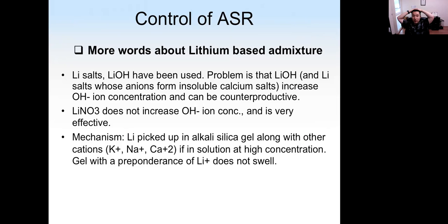So more words about lithium-based admixtures. Okay, so the problem for that is lithium hydroxide may increase concentration of hydroxide ions. So, more hydroxide ions, which may generate more potential ASR. We increase alkali concentration because of that. So if we do not use lithium hydroxide, we use lithium nitrate, so that will not increase concentration of hydroxide. So lithium nitrate is more effective compared with lithium hydroxide.